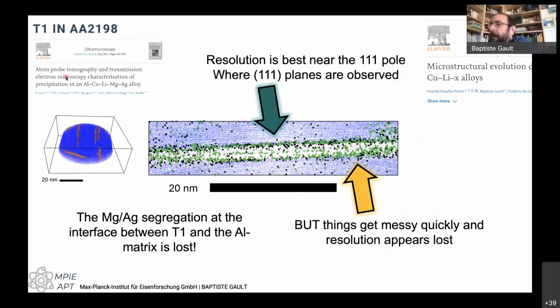There you go. So we looked at a similar set of alloys, aluminum, copper, lithium, magnesium, silver. And in that first paper in 2011, we actually thought that there was no segregation of any magnesium or silver at the interface between the precipitate and the matrix. And this is because we didn't look where the resolution was the highest.